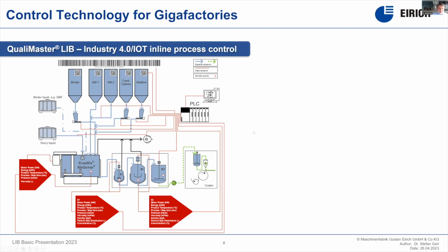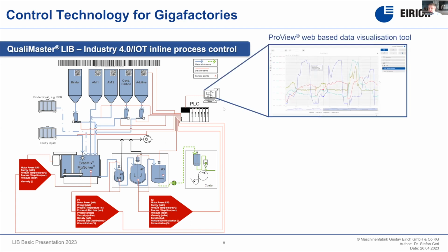All of this can be fully automated, starting with barcode readers or QR code readers for raw material identification. We are monitoring all the data coming from the dosing systems. We have the mixer with motor power, energy, temperature profile. We measure the viscosity with our inline rheometer. We have the same data out of all the tank systems, which is all collected with our PLC and can be visualized with our ProView system, which makes it easy to compare different batches, to set trend curves or tolerance bands to allow inline monitoring of the production process. The data collected can, of course, be used for data mining or artificial intelligence methods.